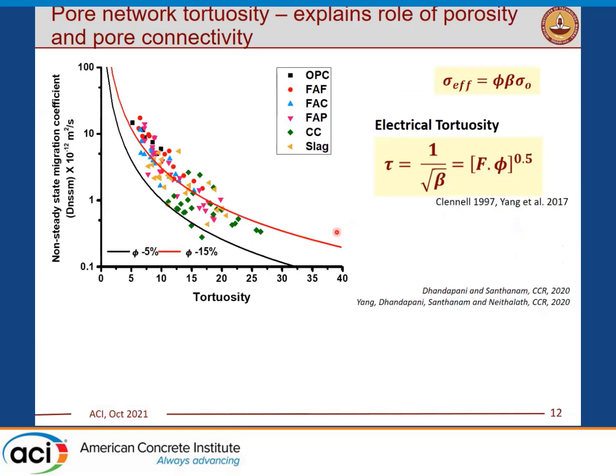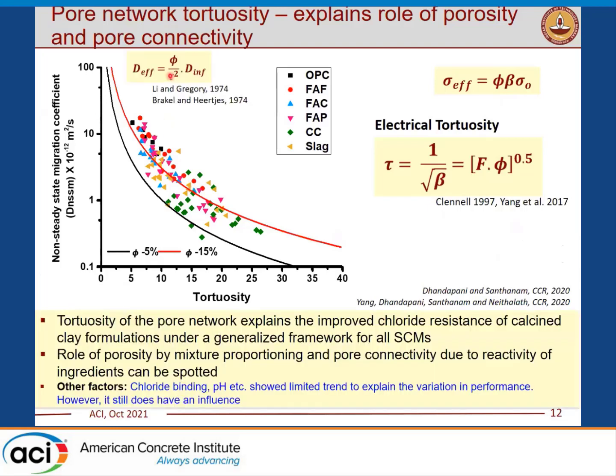So we tried to decouple the effect further, take up this porosity and pore connectivity, and estimate it in terms of the tortuosity parameter. And when we plot it, it follows a trend which is close to the tortuosity-based diffusion formulations presented in porous media literature for other materials.